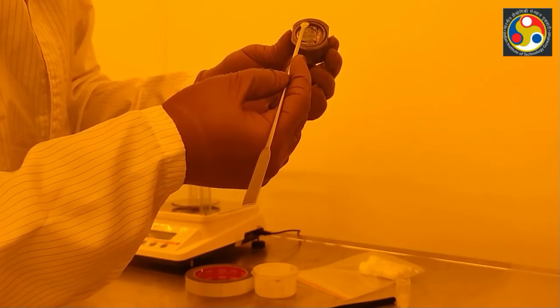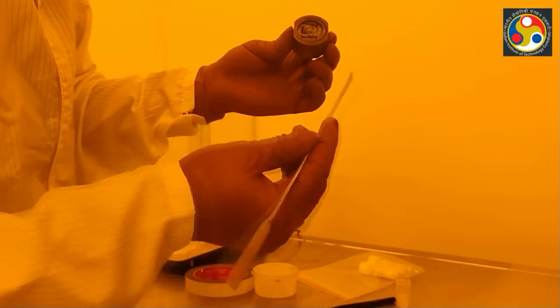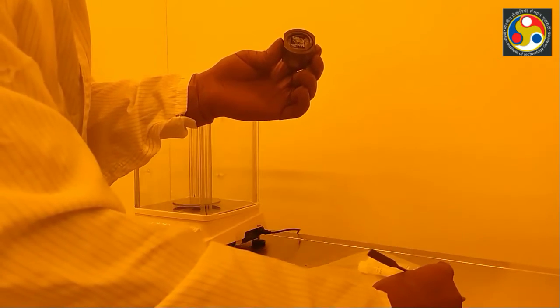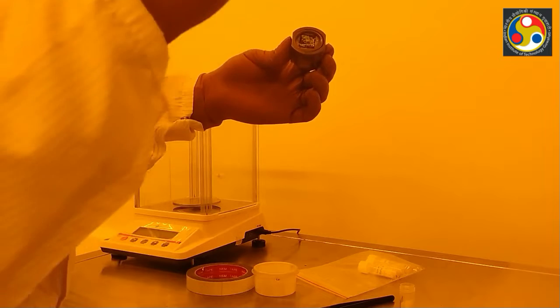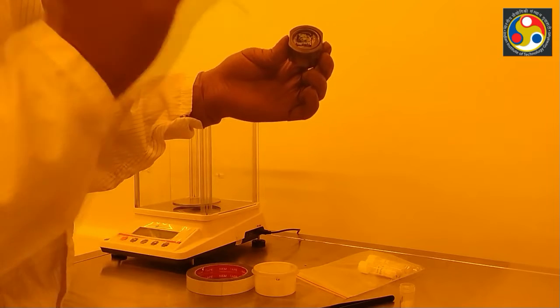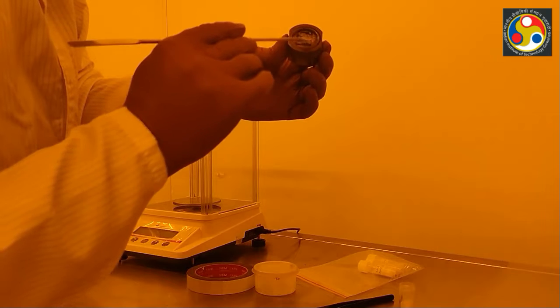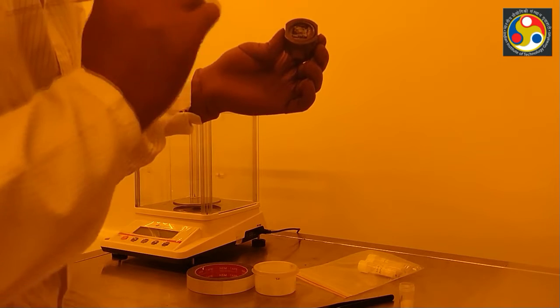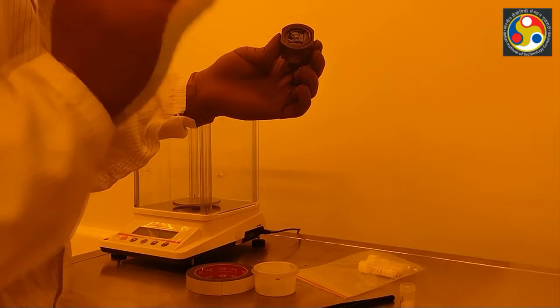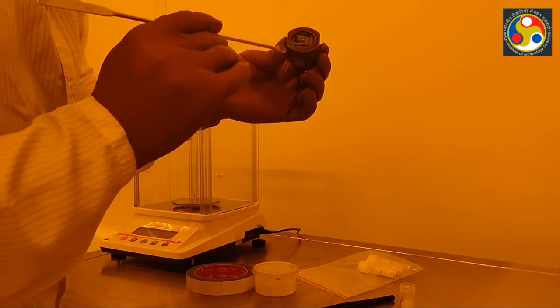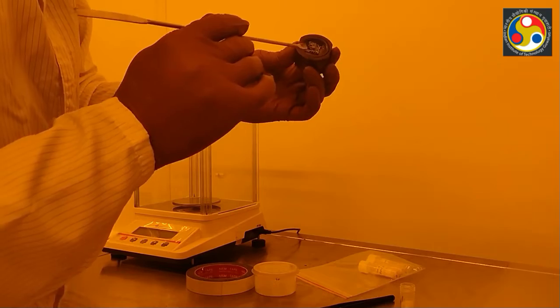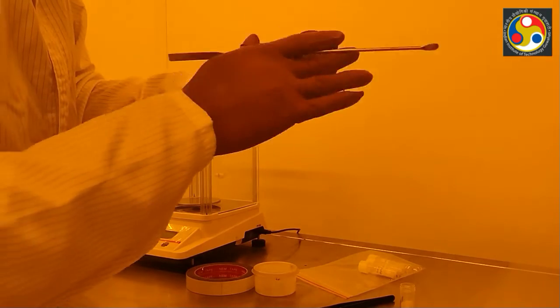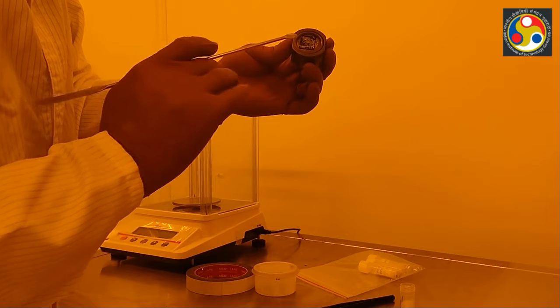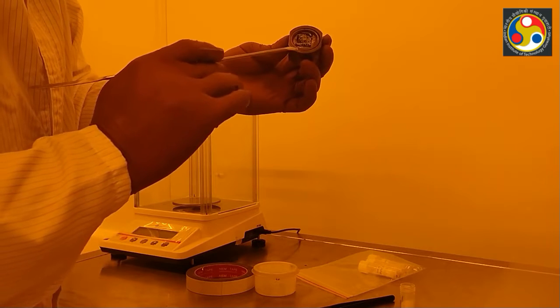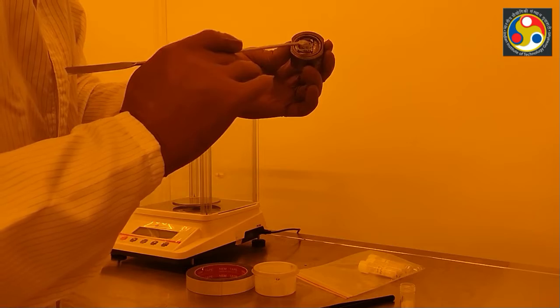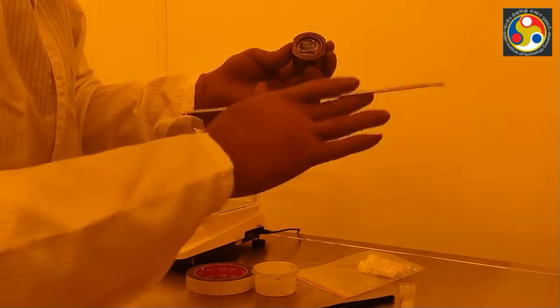Now this material is not conductive, it is a semi-conducting material, whatever my sample is. Because it is semi-conducting, and because I will be giving many electrons in this instrument, I need to coat the surface of this semi-conducting material with a conductive metal. So in this instrument we are going to coat platinum. Generally platinum, gold and others are coated to make a conductive layer above the sample if it is a non-conducting or semi-conducting sample. Now I am going to do the coating of platinum on top of this sample which is spread over this carbon tape.